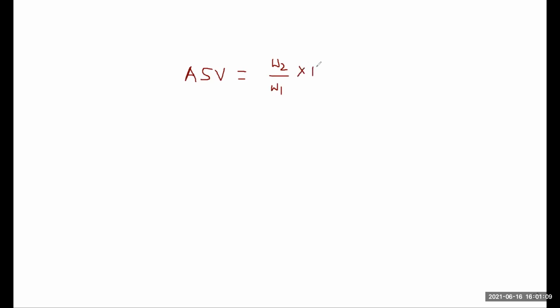So basically if we use the aggregate or a certain fraction of aggregate and repeat 5 to 10 cycles on that aggregate, then we observe our aggregate gets deteriorated, crumbled, and split. After the crumble effect, after the weathering effect, we weigh the aggregate and that weight will come out to be less than the weight which we took as our test sample. So W2 will come out to be less than W1.